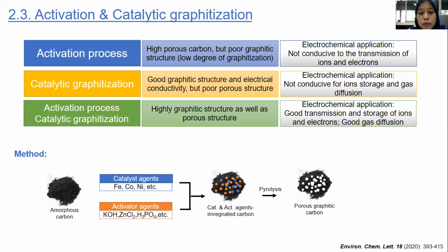The structure also provides unfavorable conditions in electrochemical applications because it is not conducive for ion storage and gas diffusion. From the previous discussion, it can be known that the promotion of the graphitization degree caused by the graphitization catalyst is able to balance the reduction of the graphitization degree caused by the activation agent. Accordingly, the combination of chemical activation and catalytic graphitization is a promising pattern of preparing BPGCs.